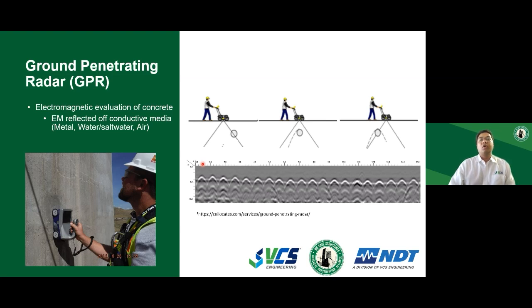So to begin with, for all the internal bonded post-tensioning systems, any investigation starts by locating the tendon, and we use ground penetrating radar to locate the tendon or the metal ducts. It's a fairly straightforward technique where you send an electromagnetic wave into the concrete and you wait for the reflections to come back. On this graphic you see here, each peak or each parabola is a presence of a steel object. That steel object can be a reinforcing steel or it can be a post-tensioning duct.